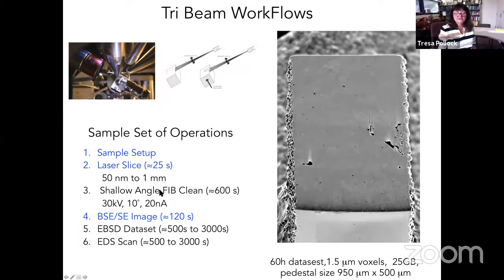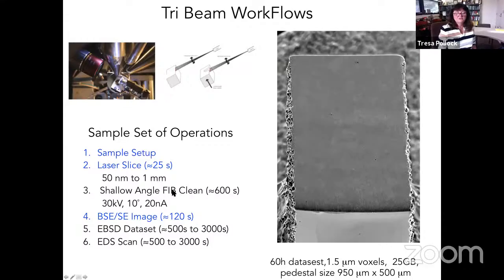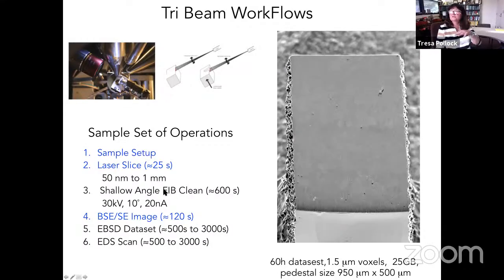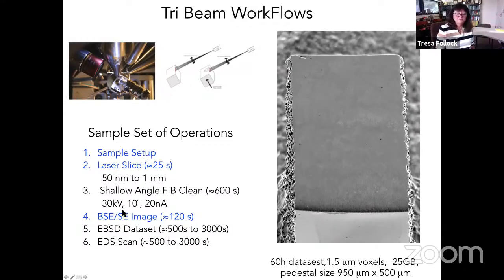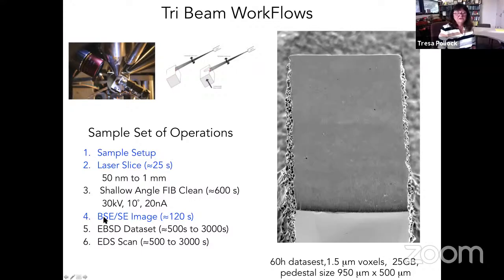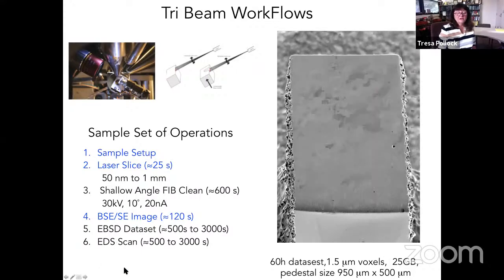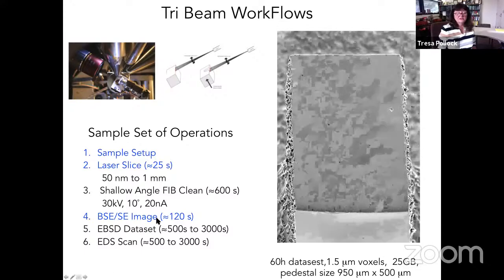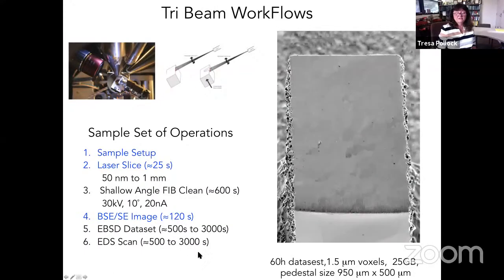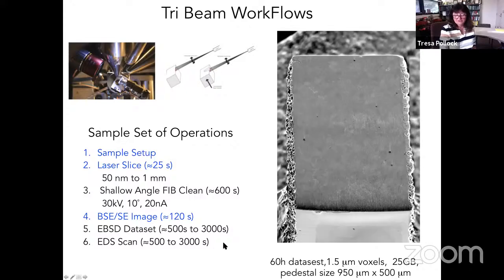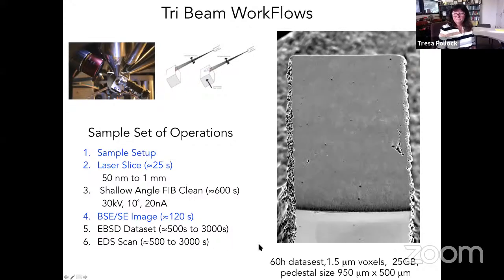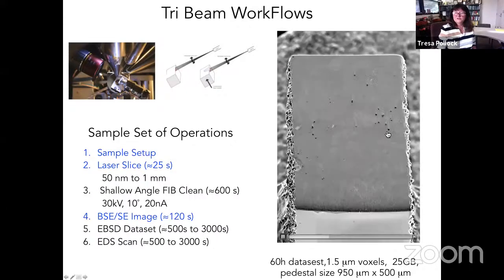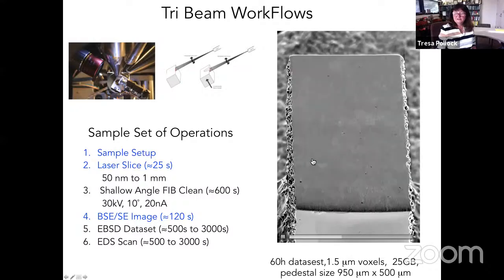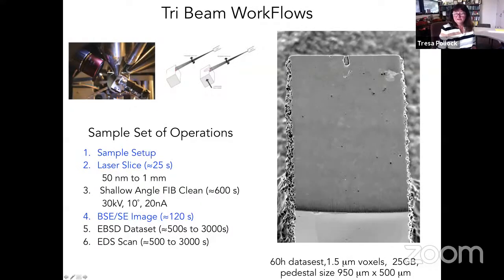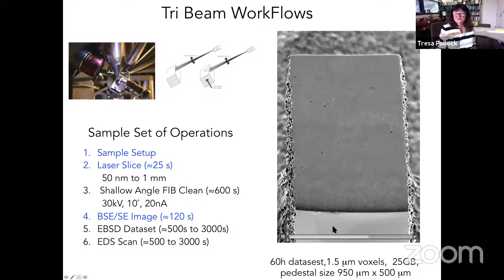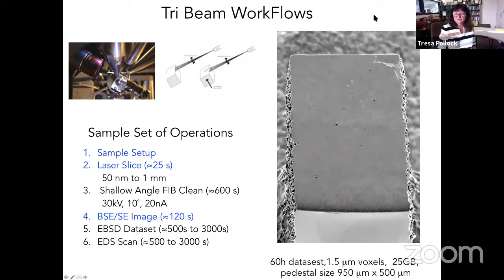In some cases, we may use the focused ion beam to slightly clean up the surface and knock off some of those periodic structures that I showed you at the surface. And then depending on what kind of information you want in each layer, one must commit varying amounts of time to gathering that data. And so as you can see here, we make a pedestal and then we remove the material layer by layer. And so this particular data set is something like almost 1 millimeter by 1/2 millimeter.